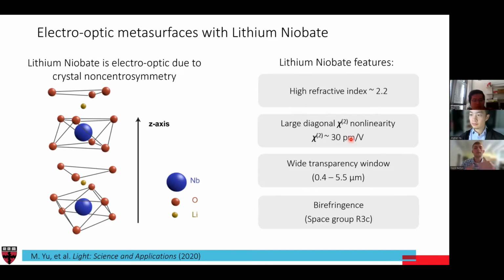And so what this means is we can apply an electric field and change the optical properties quite a bit more strongly than you'd be able to with materials, for example, like silicon. It's also a high bandgap semiconductor, which means that it's transparent over a very large window. Its bandgap, you'll start to see absorption onset around 400 nanometers, depending on how it's made, and it's transparent down to about 5.5 microns. So it covers most of the visible and certainly telecom, and also into the mid-infrared.